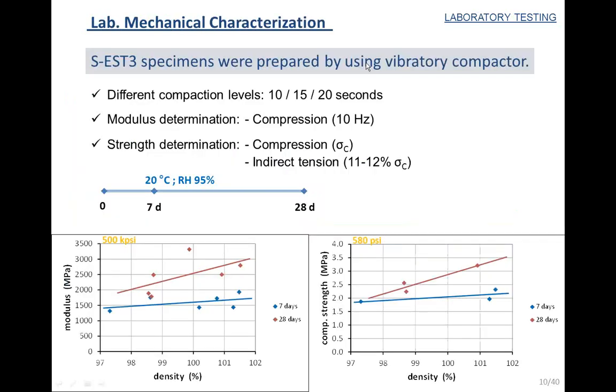Okay, we also did some laboratory characterization in order to see the modulus of the material. Probably the most important picture is this one here, the modulus versus density. We prepared this laboratory specimen by using a vibratory compactor, and then we determined the modulus in compression by applying a 10 Hz sinusoidal loading. And well, you can see here in blue the modulus evolution versus density.